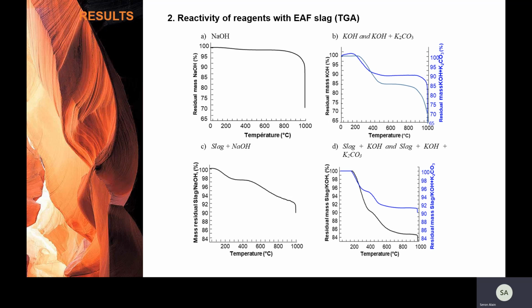In order to study the thermal behavior of the slag in the presence of alkaline reagents, a thermogravimetric study was carried out. This study was carried out in an experimental setup specifically built to accommodate large samples, making it possible to ensure the representativeness of the samples studied even when they are very heterogeneous and have a large particle size, like the slag studied here. It shows, by comparison with the thermal response of the reagent alone, that the mixture of slag and alkaline reagents, regardless of the sodium or potassium nature of the reagents, leads to a reduced mass loss after maintaining the temperature at 100 degrees C for 1 hour.